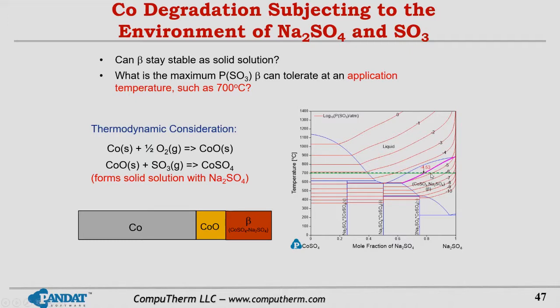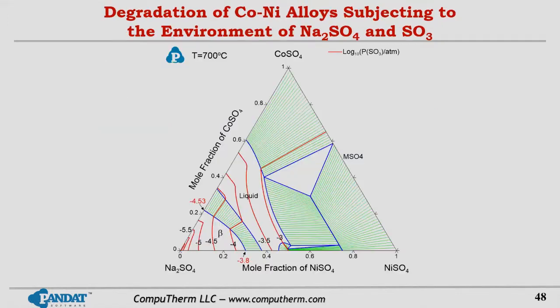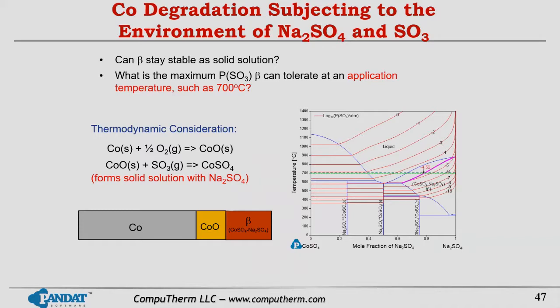However, if the partial pressure in the environment is higher than this 4.53, then liquid will come out, which will make this material completely corroded, so it will become liquid on the surface. So that's the binary, pseudo-binary system.